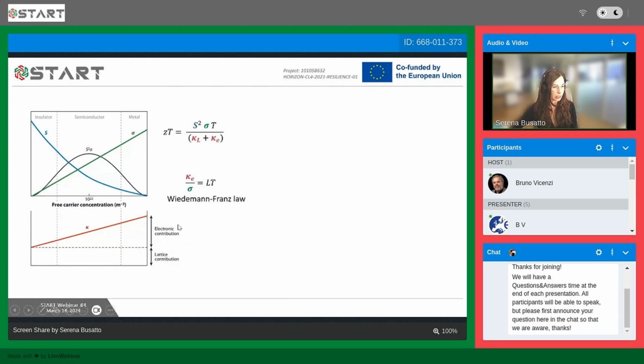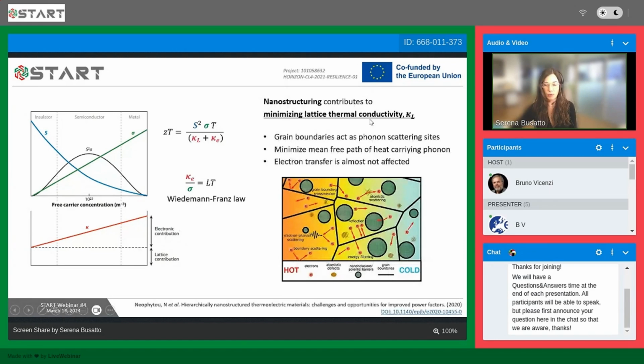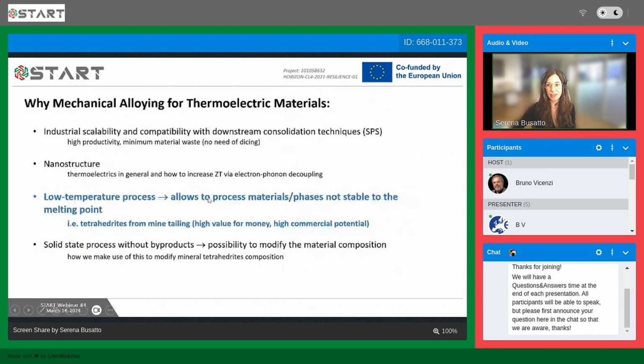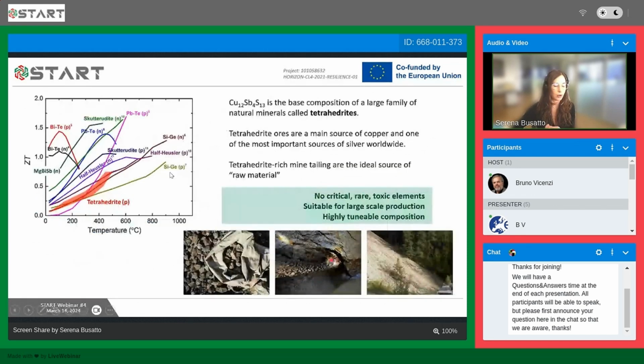And we can do so by nanostructuring, because the grain boundaries act as phonon scattering sites, and minimizing the mean free path of heat-carrying phonons can minimize thermal conductivity, while the electron transfer is almost not affected by this. Let's proceed then to talk about the tetrahedrites and how these materials can be treated by mechanical alloying or mechanochemistry.